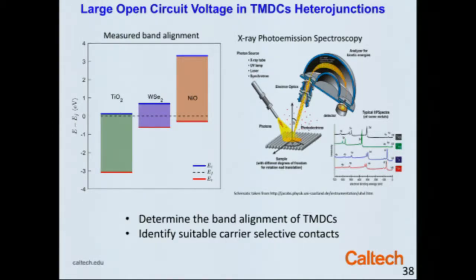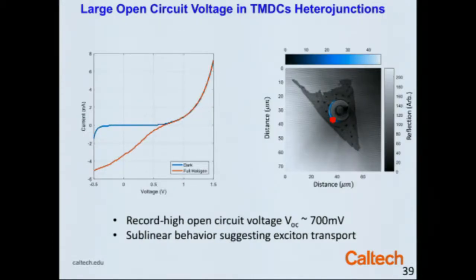We looked at many other materials as well, I won't tell you about in detail. But by choosing these in such a way that nickel oxide blocks electrons but collects holes, and titanium oxide blocks holes but collects electrons, you can see they're not perfect, because a perfect material would have its conduction band aligned with the conduction band of the semiconductor, and nickel oxide aligned with the valence band of the semiconductor.